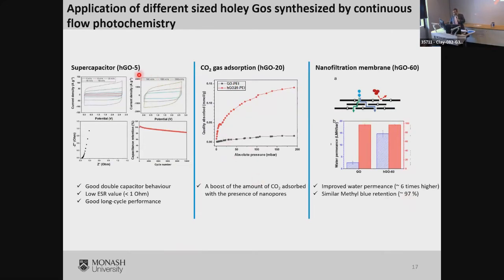For example, holey graphene oxide with 5 nanometer pores, we were able to demonstrate its use as a supercapacitor. Pretty good performance compared to what we know. And then recently we learned that about a 20 nanometer holey graphene oxide is really good for carbon dioxide adsorption. And then again, about 60 nanometer pores are ideal for nanofiltration application, where we get rid of smaller molecules. We increase the permeance by a factor of 6.